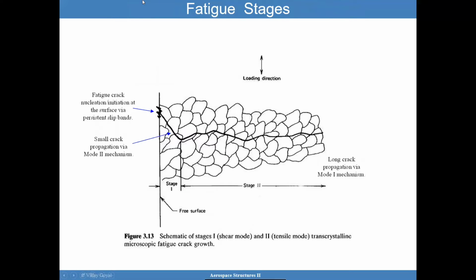So what are the fatigue stages for crack growth? If this is the loading direction, we will have the stage 1 crack propagation, and the fatigue crack initiation will occur via persistent slip bands. And the small crack propagation will be via a mode 2 mechanism, meaning that the surfaces are sliding relative to each other, regardless of the fact that we're loading in the mode 1 direction. So even if the loading is perpendicular to the sample, the crack will start as a mode 2 and then start moving into a longer crack propagation via mode 1 mechanism. Mode 1 here means it opens the crack. Mode 2 means it's sliding. The surfaces are sliding past each other.